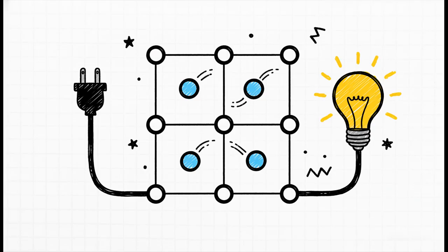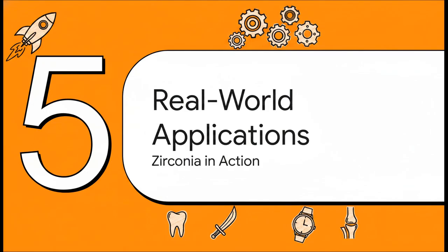Physical strength isn't its only superpower. Remember that fully stabilized zirconia we talked about earlier? By flooding the recipe with 8 to 10% yttria, scientists don't just freeze the cubic structure, they actually alter the atomic lattice itself. They create these missing spots called oxygen vacancies. So at high temperatures, oxygen ions can rapidly hop from vacancy to vacancy right through the solid ceramic. This transforms the material from a standard heat insulator into a fast oxygen ion conductor. It essentially becomes an electrical component. Which perfectly segues into Section 5, Real-World Applications.